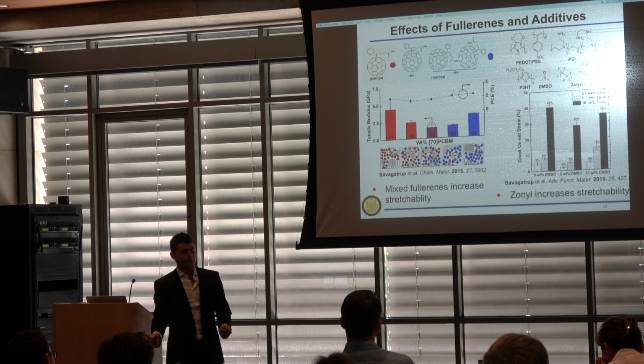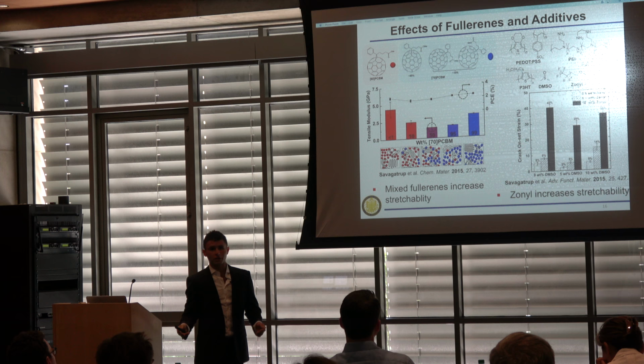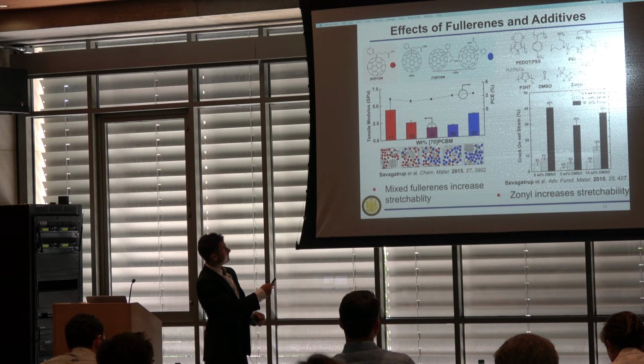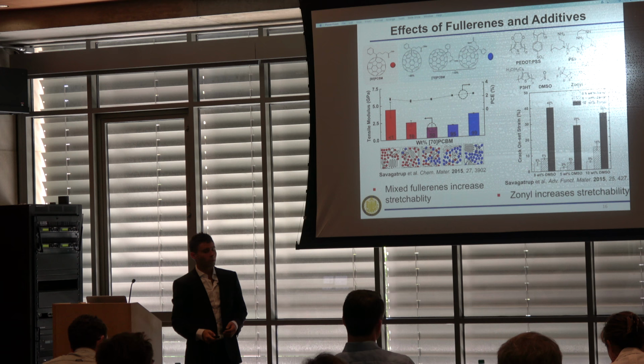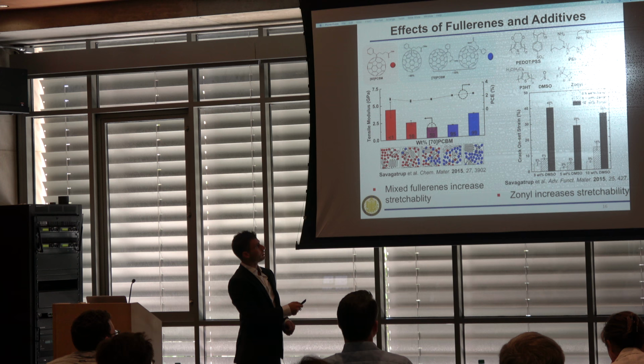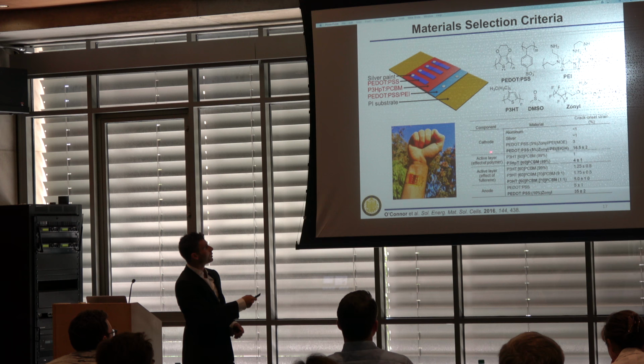But if you use a mixed phase, you actually have a much lower tensile modulus, and you can stretch them a little bit further. And this is because they don't pack in as well, with the differences in shapes of the nanostructures. So mixed fullerenes increases stretchability, and then with PEDOT, if you add Zonyl, you can plasticize the layer without negatively affecting the conductivity of the film. So Zonyl increases stretchability.